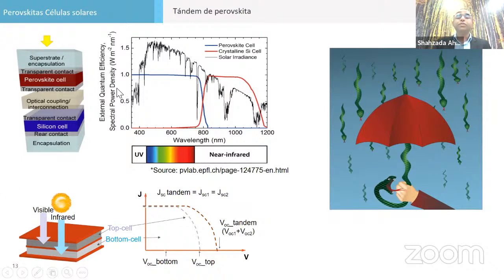If you look at the wavelength here, we absorb very well in the UV-visible up to 800 nanometers. From 800 to 1200 or more, the silicon solar cell, the bottom cell, can absorb. So if you shine a light, the perovskite solar cell can be the top cell and absorb the light, and the bottom can be a silicon cell. By doing so, the voltage increases, the current is also high, and we have almost 30% efficiency that people have reported. Top cell and bottom cell, it's called the tandem approach.